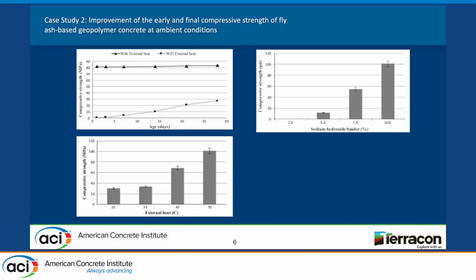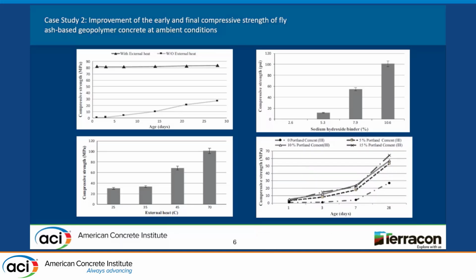So I introduce using Portland cement as a partial replacement. So I use 5%, 10%, and 15%. I just replace the fly ash by 5% of Portland cement, 10% or 15%. And you can see here we improve, and this is without any external heat. And you can see here the early compressive strength was really improved, and the final compressive strength without any external heat was more than 60 megapascal, which is around 9,000 psi, and it's really good.